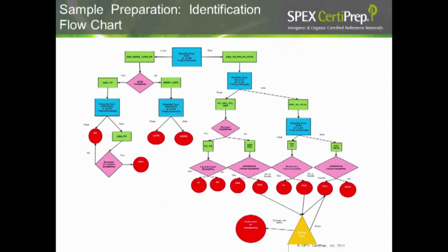Overall, it came down to a spreadsheet or a flow chart that looked like this. And don't worry if you can't read all the fine print. I'm going to go into a little bit more detail, but this is the overall scheme of things. The blue boxes were density tests, where we tested the plastic against a certain density standard. The pink diamonds were solubility tests, where we tried to dissolve our plastics in some different types of solvents to see if they were soluble or not. And the yellow triangle at the bottom was a flame test, where we actually set fire to some of the samples using a copper wire and observed what type of residue, smoke, or flame color it produced.